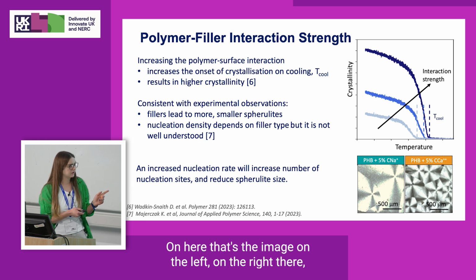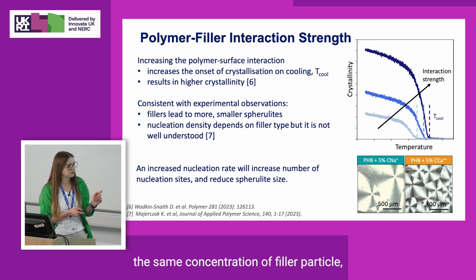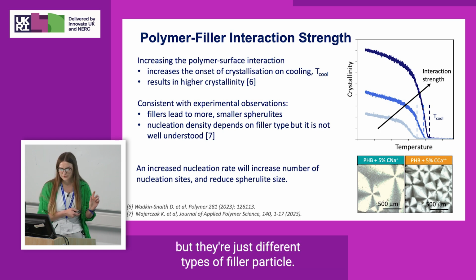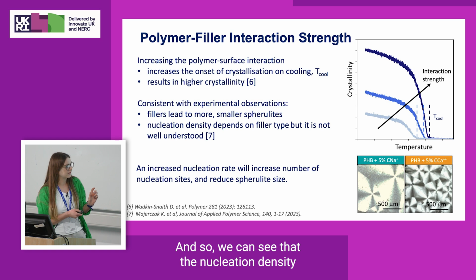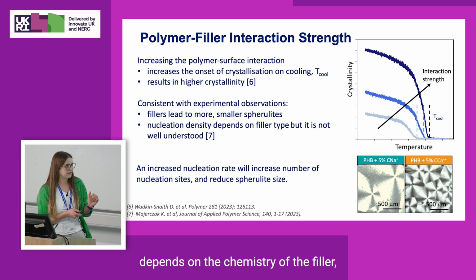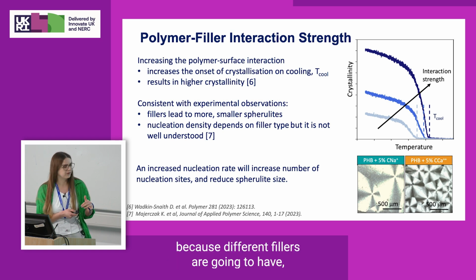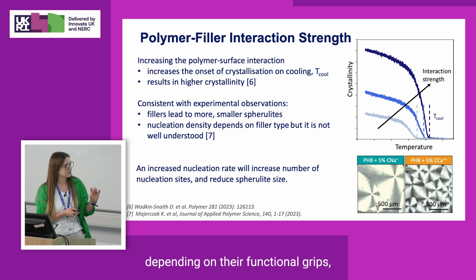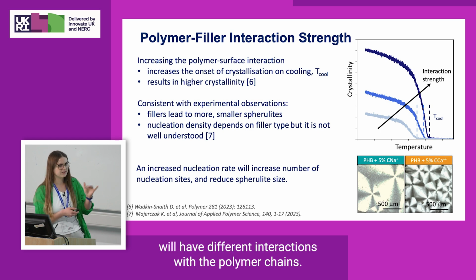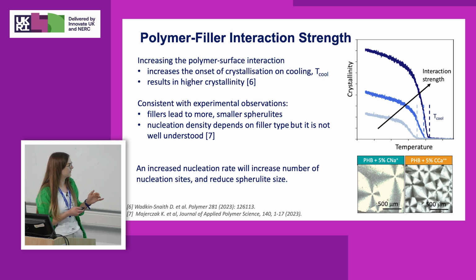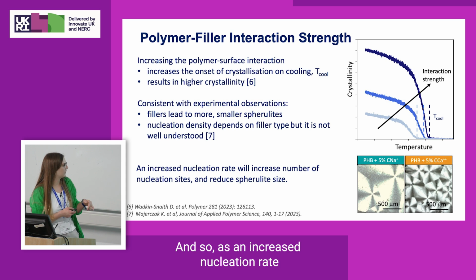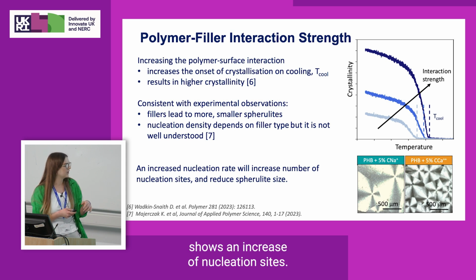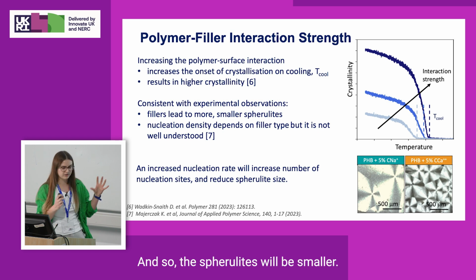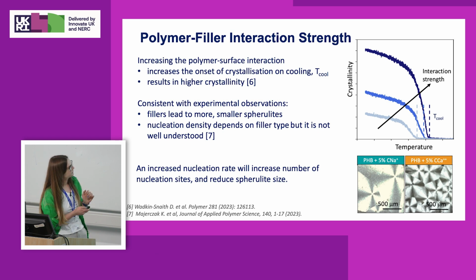The image on the left and the right are the same concentration of filler particle, but they're different types of filler particle. And so we can see that the nucleation density depends on the chemistry of the filler, because different fillers, depending on their functional groups, will have different interactions with the polymer chains. And so an increased nucleation rate will show us an increase of nucleation sites, and so the spherulites will be smaller.